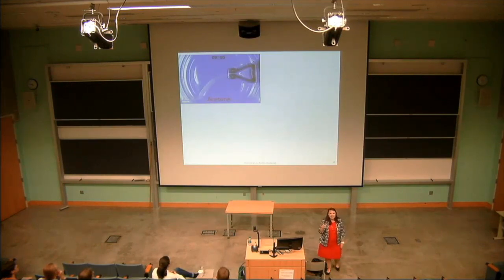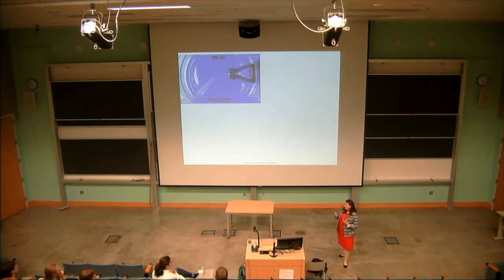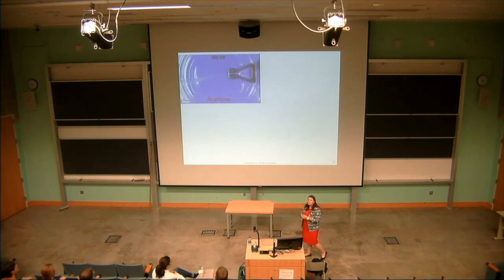Now, what happens is as you continue to place it in acetone, and as it's continuously exposed to this, the PDMS is going to swell. Simultaneously, your hydrogel is going to de-swell. So we have our PDMS sitting up here on the top. We have our hydrogel along the bottom. And then this simultaneous swelling and de-swelling is allowing the entire structure to bend downward.